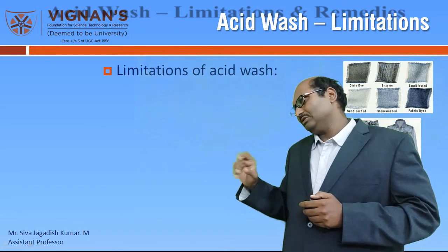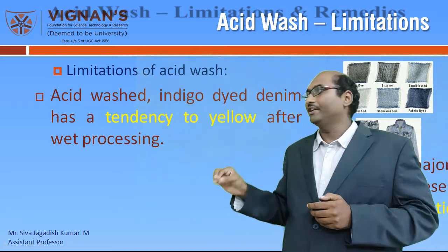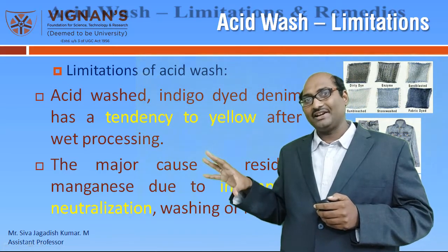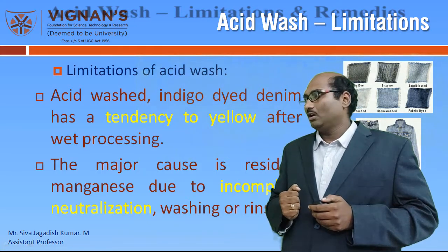So it has its own advantages, like unique textures being created, but some limitations and remedies we will also discuss. A limitation is that acid wash indigo dyed denim has a tendency to yellow after wet processing. Wherever this white area is there, that is basically due to back staining. It tends to yellow, and it is not recommended by certain buyers.